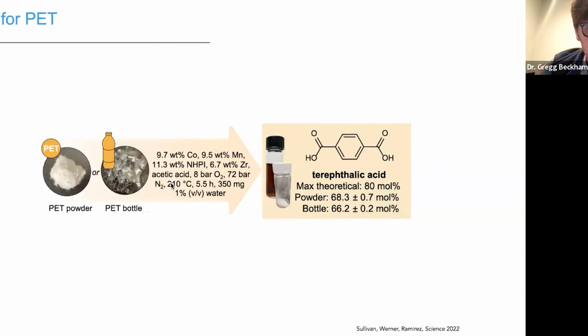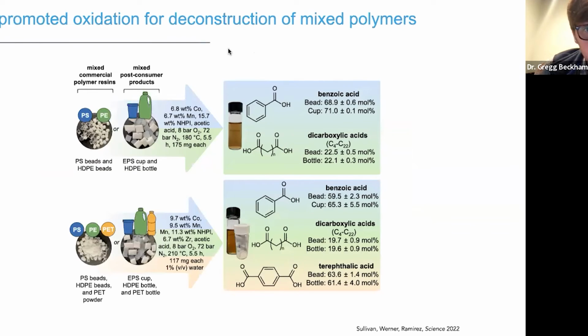And for PET, again, and these are all the optimal conditions I'm showing you now, at 210, for 5.5 hours, we're able to obtain around 68% or 66% of terephthalic acid as a single product from PET depolymerization through this auto-oxidation process. When you mix these together, shown on the top is for polystyrene and HDPE.